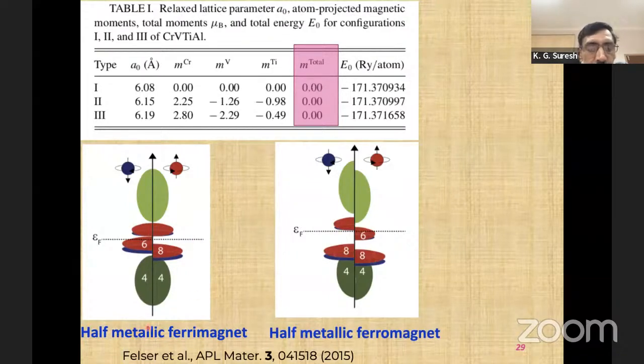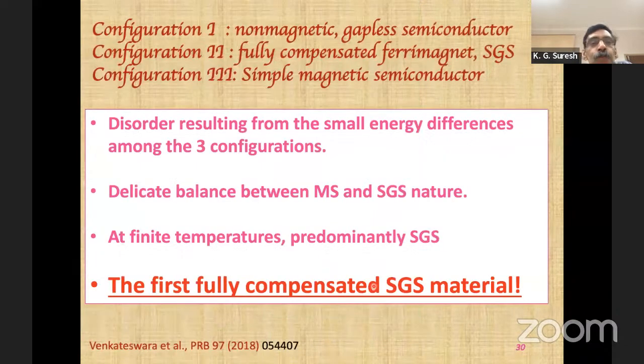So that is the difference between the spin polarized band structure for a half metallic ferrimagnet versus that of a ferromagnet. In this particular case, we could identify that it's actually a fully compensated ferrimagnet, as I mentioned. And also it has a magnetic semiconductor and spin gapless semiconducting property.